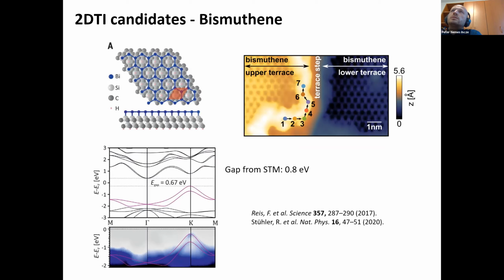And recent experiments have shown that something very similar can be grown on top of silicon carbide. So this is not purely a 111 bilayer of bismuth, but it's basically a chemical compound between the silicon carbide surface and the bismuth, where the bismuth forms this honeycomb lattice, and the gap that was measured from STM is of the order of 0.8 electron volts, so very, very large.